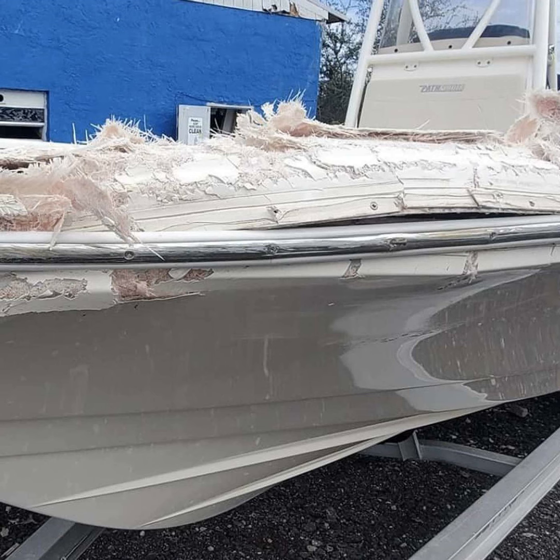So you've catalyzed your resin, you've started applying your mat, then you've added your 1708. You're going to use a little metal bubble roller, bubble buster, to work out any bubbles as you go. And then once you're approaching the last layer, I like to finish all my repairs with a layer of chop strand mat too, provided I'm pretty close to landing on grade. That is, then I can grind that back a little bit, scuff it back, or maybe in some high spots, grind through it, and then go over that with a layer of fairing. And that lets me start the body working process, where I'm transitioning out of my fiberglass repair and into the realm of cosmetic repair.